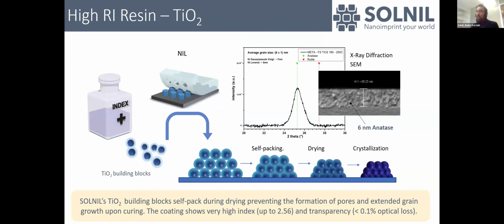So now, how did we achieve such high and low refractive index? The high refractive index, we obtain it using a specific TiO2 formulation. We start not with nanoparticles, it's something smaller. We start with molecular precursors, and we have building blocks which are quite specific. They have a kind of hard core and a kind of soft shell.